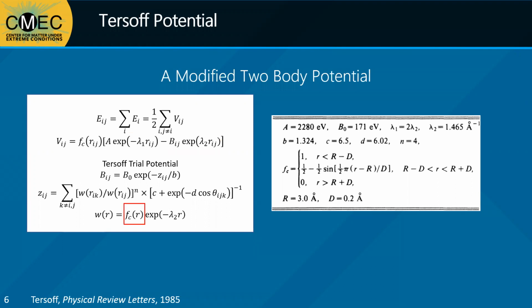F sub c is the cutoff function, which limits the range at which atoms will interact with each other. This substantially lowers the computational load of the simulation. Tersoff's initial parameterization values for the potentials are seen on the right, and these more faithfully model the elastic properties of silicon compared to the potentials that came before it.